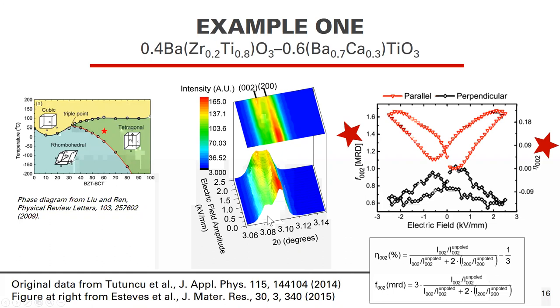You can fit those peaks, another topic that we're not going to talk about today, but could be the subject of another hour-long seminar. You can fit those peaks, extract the intensities, and calculate these metrics. And you can represent them on a plot of pole density, F002, or domain switching fraction, eta, as a function of electric field amplitude. And here you're seeing two measurements. The red data represents the scattering vector parallel to the electric field. And we can see that we start out in the initial unpolled state. MRD is one and the switching fraction is zero. And as we apply an electric field, you can see that this indicator increases, showing you that the domains are aligning on a volume fraction basis with the applied electric field, and the overall shape of this mimics the hysteresis loop, which you might expect.